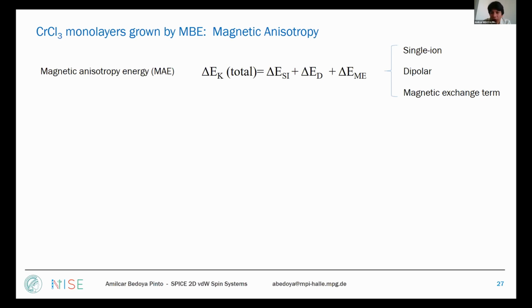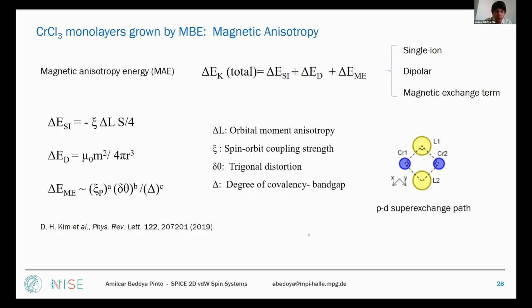So to understand these anisotropy fields, it's good to look at the anisotropy energy that's composed of three terms: the single-ion term, the dipolar term, and the magnetic exchange term, following here one recent paper that argued that this component would be also important to explain the anisotropy of this trihalide. I just very briefly tell you what the important parameters here are. This is the spin-orbit coupling strength. This is the orbital moment anisotropy. For the dipolar term, everything is relatively simple. But here, there's also the degree of trigonal distortion that will come into play.